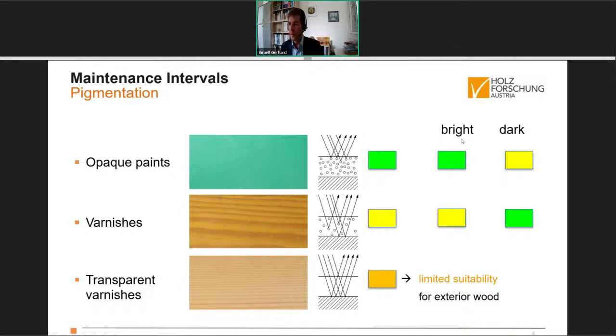In the early work, we already figured out that bright colors for opaque paints last longer than dark colors. This is due to more heat built up, due to the absorption of sunlight energy of these surfaces, and a quicker tendency to cracking of dark surfaces in exterior use. With varnishes, with the semi-transparent systems, in contrast, we found out that darker pigmentation is of higher durability compared to brighter pigmentation. This is due to better UV light protection.